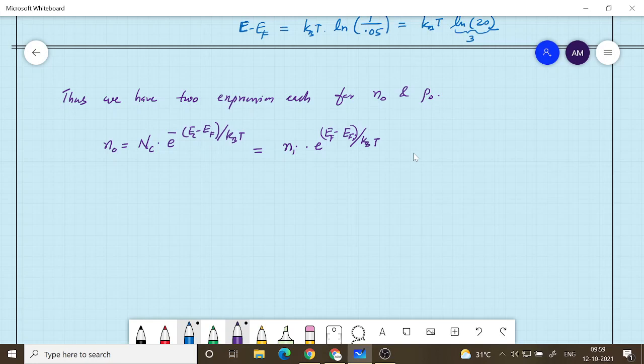And similarly P0, I can write it as NV, this is yesterday's formula that we derived, into e raised to minus of (EF minus EV) by kBT. I can also write it as, since Ni and Pi are the same, Ni into e raised to (EFI minus EF) by kBT. Okay, so if you look at these formulas, these are two alternate formulas. One is with respect to the effective density of states, and the other is with respect to intrinsic carrier concentration.